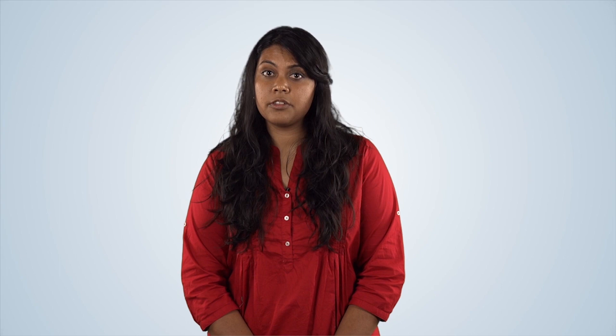When we use the PECVD, we typically use standard recipes for deposition of thin films. We choose the recipe for the material that we want to deposit on the computer, as well as the desired deposition time. The deposition time determines thickness of the deposited material. Typical thicknesses of PECVD films range from tens of nanometers to a few microns. Each process is calibrated so that the deposition rate for each material is known. For example,